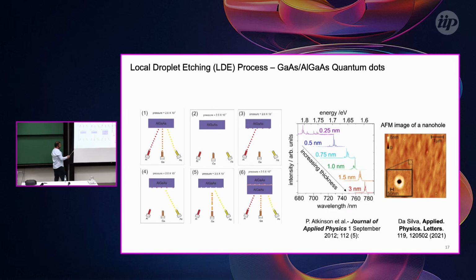But if you control the arsenic background, if you change this, like increasing it a little, instead of crystallizing these droplets, the droplets start etching the GaAs surface. And with this, we can make these nanoholes. And after making these nanoholes, we can fill them with gallium arsenide. In the next steps, we close with the AlGaAs barrier, and we will be able to confine the electrons inside these nanoholes, and this will be our droplet etching quantum dots.